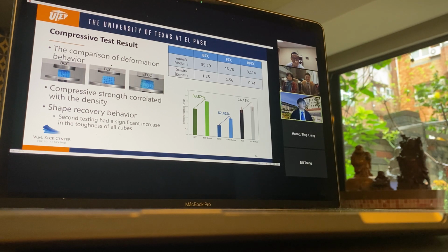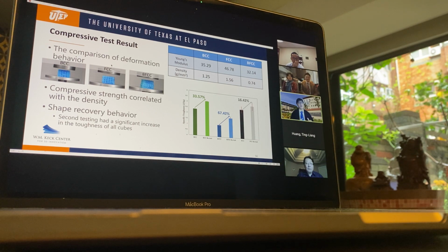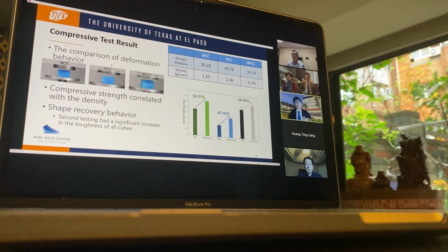So as these three pictures show, after the testing, the difference in the deformation mechanism between them is not obvious through our visual inspection. In general, we can categorize FCC as being stretch dominated, making FCC the hardest cube among them. And BCC can be seen as a bending dominated pattern. The deformation is very uniformly divided into the whole structure. BFCC is not a symmetric structure of the unit cell. That's why BFCC will have a distorted deformation, like this picture shows.